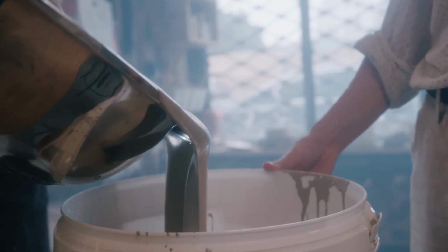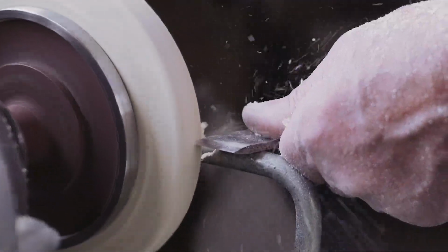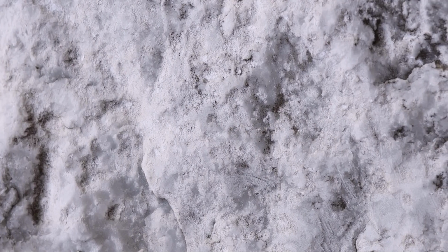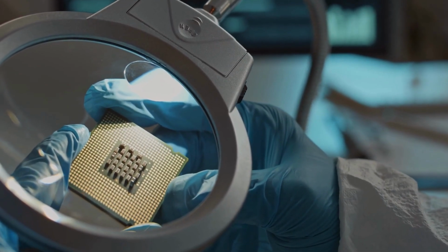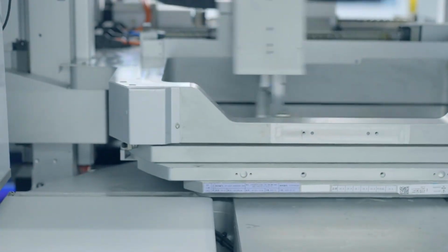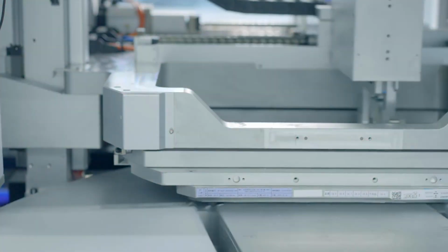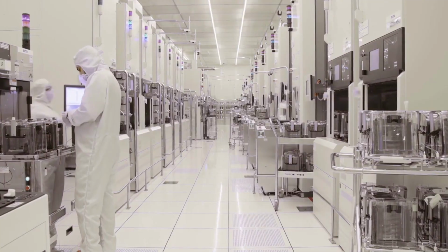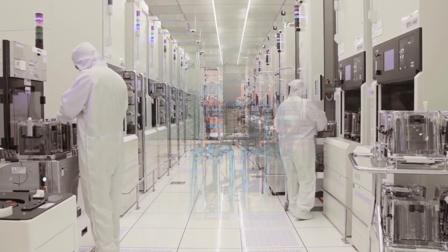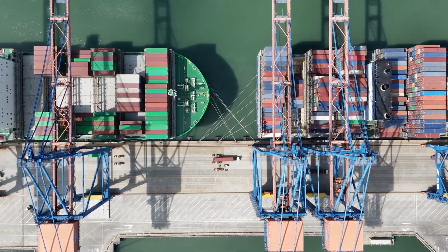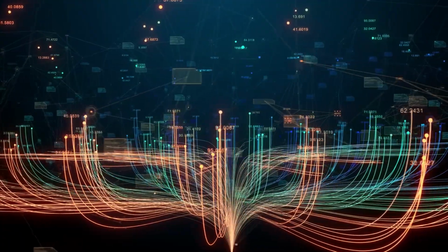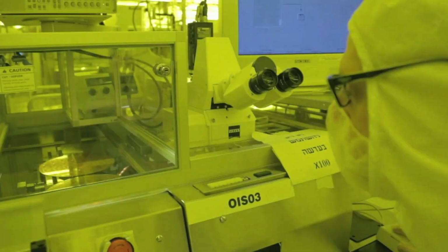This step is called chemical-mechanical planarization, and it is not a gentle process. It uses a slurry of abrasive chemistry pressed against a spinning wafer to remove material with atomic precision. The surface roughness that comes out of this step has to be below roughly half a nanometer. If it is not, the bond either fails or performs at lower yield. The incumbents in chemical-mechanical planarization equipment are Applied Materials with their Mirra and Reflexion platforms and Ebara of Japan. This is where Applied Materials lives in the story, not at the bonding table, but in the prep kitchen.